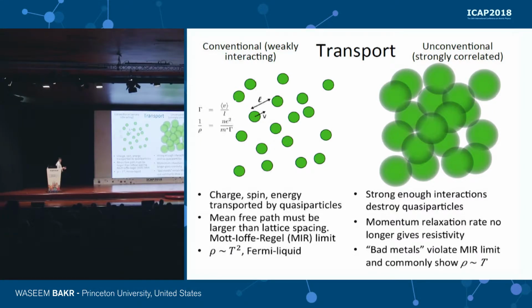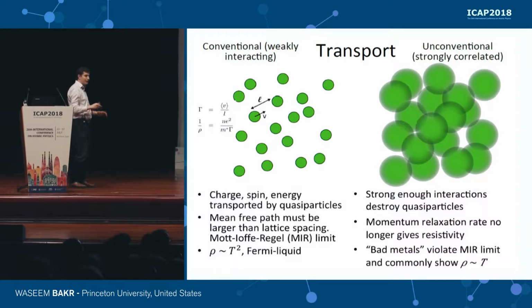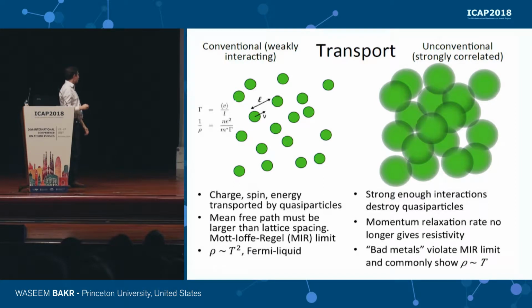Now in a good metal, this mean free path will be pretty long. And as we increase the temperature, it will start to shrink. If we're working in a clean system where there's no disorder, and if we assume there's no phonons, as is the case in our experiments, then this mean free path can be bounded. Clearly, it cannot be shorter than the interparticle spacing.